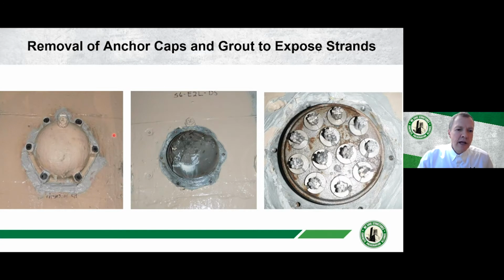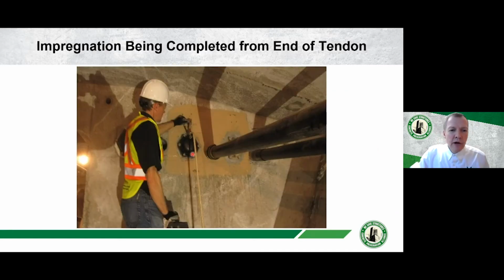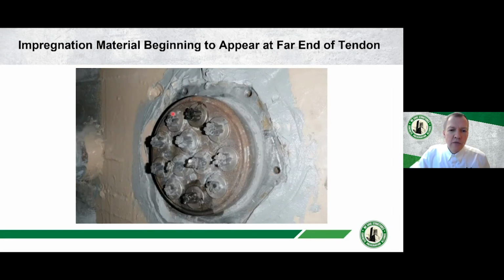There are plastic end caps, and if you have this condition, a simple way to do this is to remove the plastic or metal end cap, expose the grout, remove the grout, expose the end of the anchorage and the end of the strands, put the cap back on, connect a hose to the grouting port, fill the cap with the impregnation material, pressurize it, and then go to the other end of the tendon where you've done the same removal and cleaning, and just wait until the material begins to appear there.